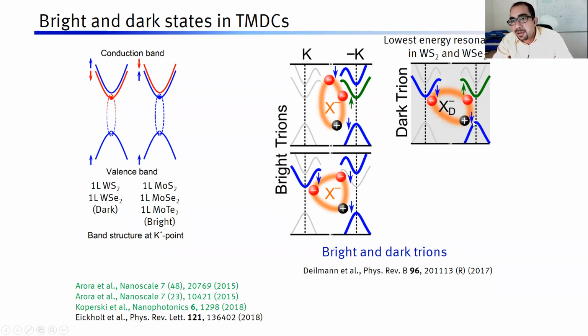However, if at the same K point of the Brillouin zone, you have an upspin in the conduction band and a downspin in the valence band, then this is a dark state. Then this is a dark exciton. Then you can place another spin somewhere, and this will be a dark trion. So the point is that this dark trion has the lowest energy in the spectra of this tungsten-based material.